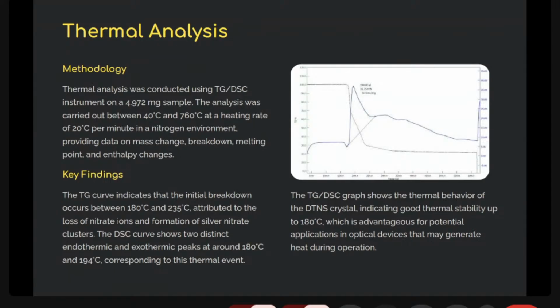Thermal analysis was carried out between 40 degrees and 760 degrees Celsius at a heating rate of 20 degrees Celsius per minute in a nitrogen environment. There are around 4.9 milligram in the sample. As you can see in the figure, the TG curve indicates the initial weight loss, which is attributed to the loss of nitrate ions and the creation of silver nitrate clusters that take place between 180 degrees Celsius and 235 degrees Celsius, and two distinct endothermic peaks are observed at 180 degrees Celsius as well as at 194 degrees Celsius in the DSC curve.